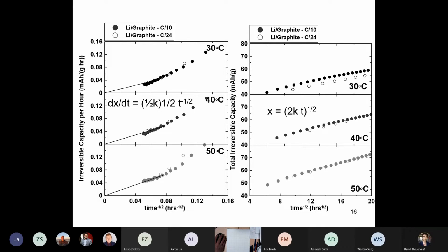So they would make them, they would do their formation, and then they would sit at 50% state of charge at 45 degrees C for some period of time, like a week or 4 days, I don't remember. But the whole point of that was to thicken the SEI so that when the cells were given to the customer, the initial capacity fade at room temperature was basically not measurable because you've already thickened the SEI quite a lot. So history, as well as temperature and additive, all these things affect the SEI growth rate.